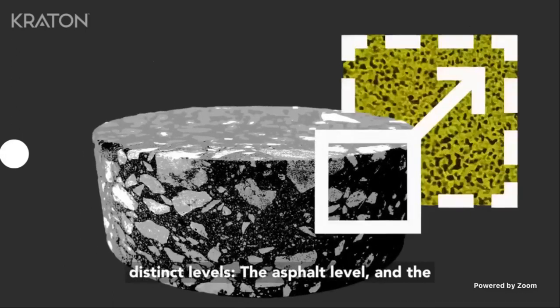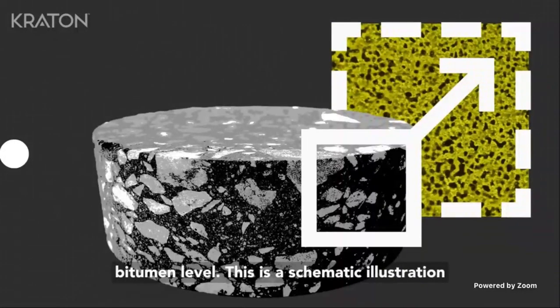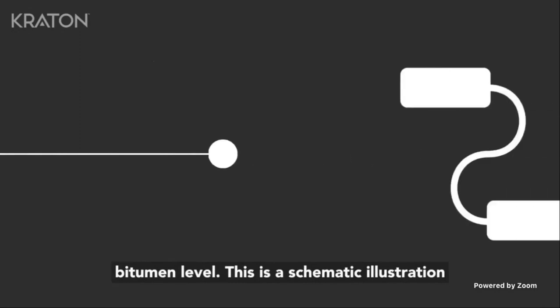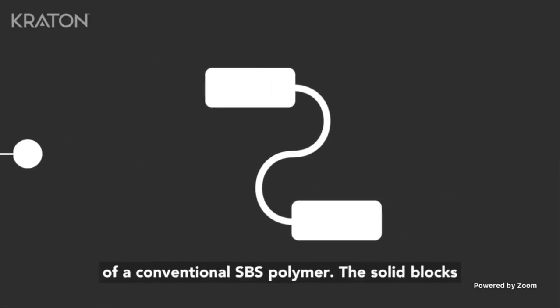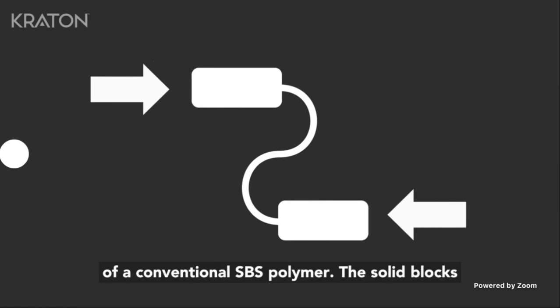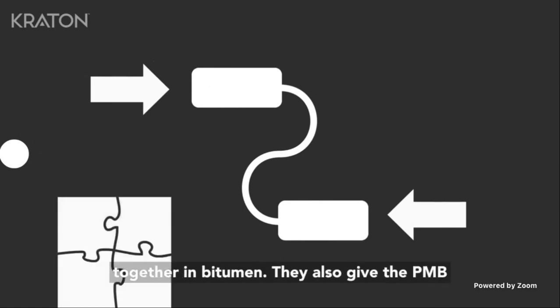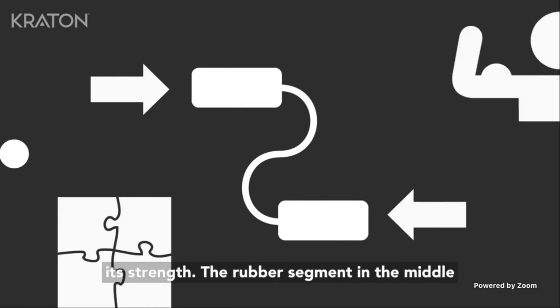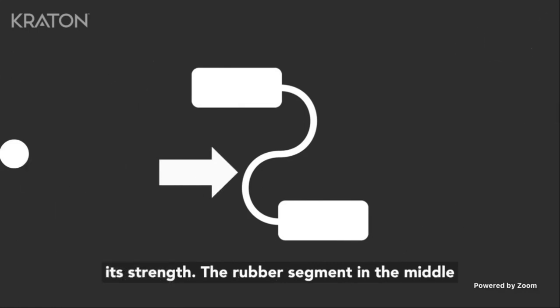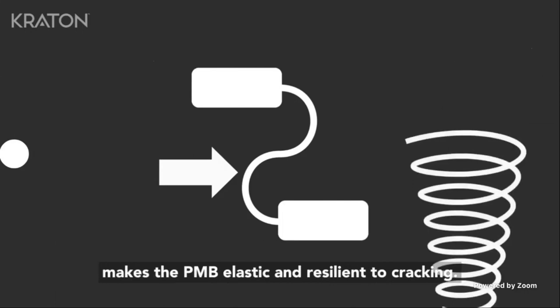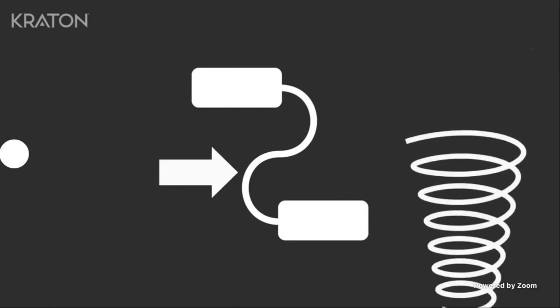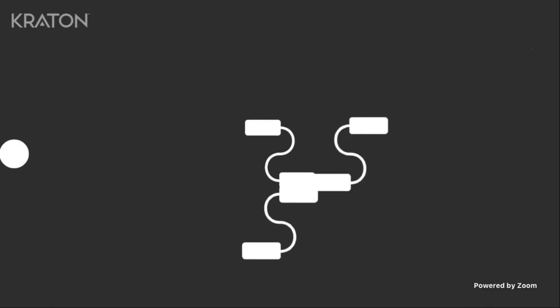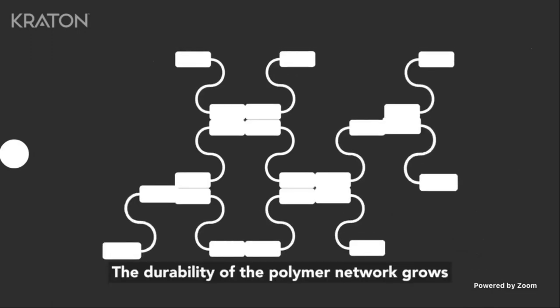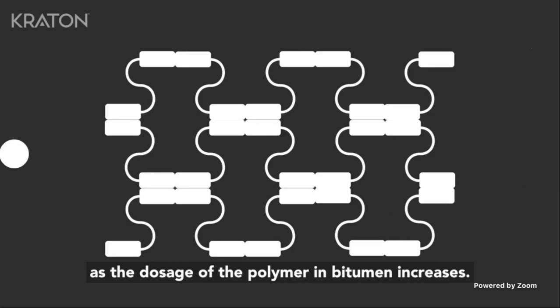HiMA should really be understood on two distinct levels: the asphalt level and the bitumen level. This is a schematic illustration of a conventional SBS polymer. The solid blocks on both ends allow the polymers to assemble together in bitumen. They also give the PMB its strength. The rubber segment in the middle makes the PMB elastic and resilient to cracking. The durability of the polymer network grows as the dosage of the polymer in bitumen increases.